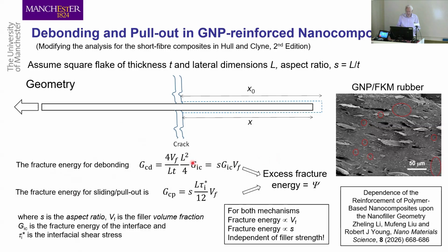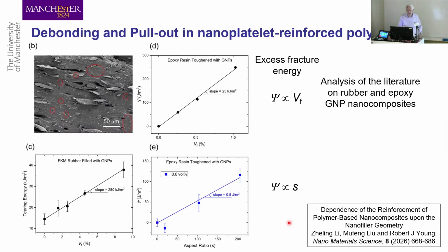The energy for debonding is given by this equation. Again, depends on the aspect ratio. And the fracture energy for sliding and pull out is again by this equation, again, depending on the aspect ratio. Aspect ratio appears all the time in these analyses. So what you'd predict was the fracture energy is proportional to the volume fraction, and fracture energy is proportional to aspect ratio. So if you look at fracture of various nanocomposites, this one is epoxy toughened with GNPs, proportional to the volume fraction, the excess energy, tearing energy of a rubber, proportional to volume fraction, tearing energy proportional to aspect ratio. So it all sort of works out quite nicely on standard conventional theory.